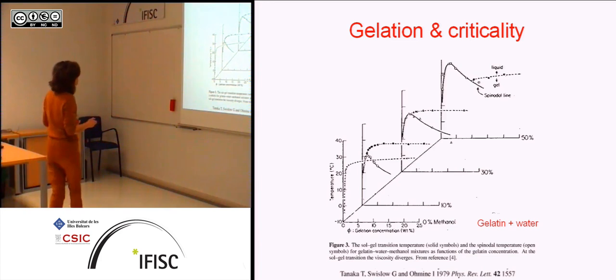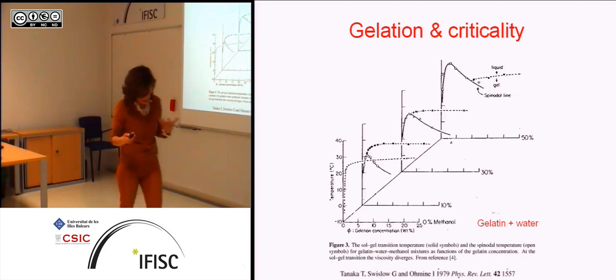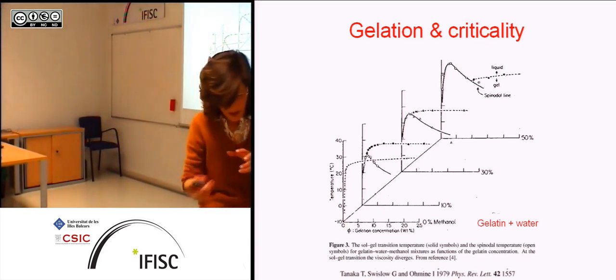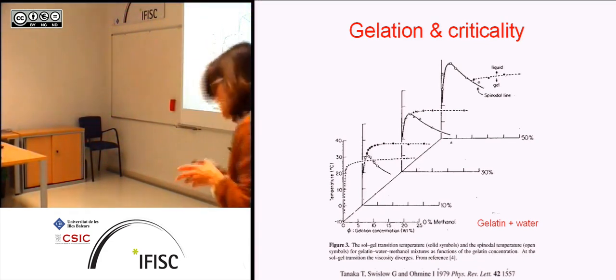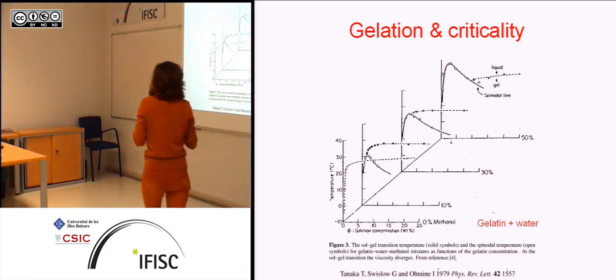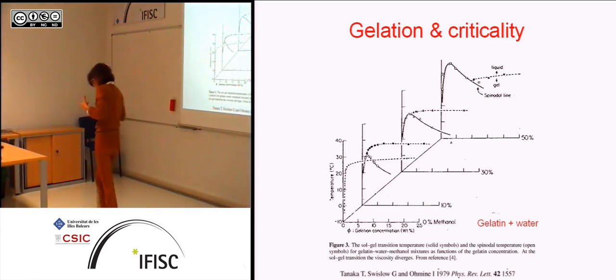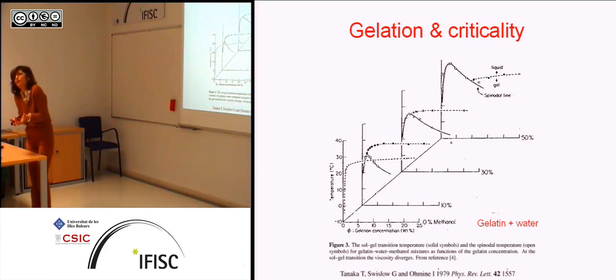But now, see how this gel transition seems to, depending on the concentration of alcohol, emerge from the critical point of phase separation, or if you like, the critical point to emerge from this percolation line, and in other cases it doesn't. And we want to understand a little bit better, if we can, how these thermal phase transitions have to do with this gel forming, which is the structure of the fluid after all.